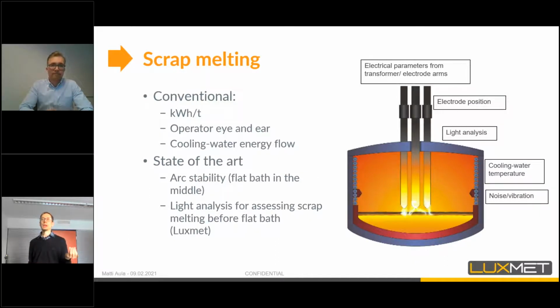When you measure the scrap melting, the most conventional method is just to observe the kilowatt hours that you have put into the furnace compared to the charge amount in tons, for example. Another very traditional method is just to hear the furnace. When the arcs get uncovered, the sound of the furnace starts to increase. And subsequently, if you start the arc foaming, the noise of the furnace will start to go down when the arcs are covered with the foaming slag. Also, one method which practically every furnace uses is the cooling water energy flow. We never want our side panels to overheat because this causes a serious risk of water leaks, which can be critical and even catastrophic in some cases.